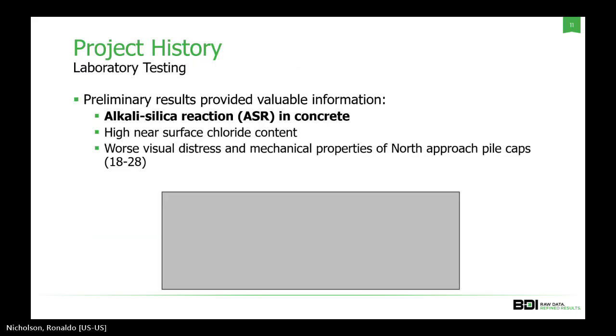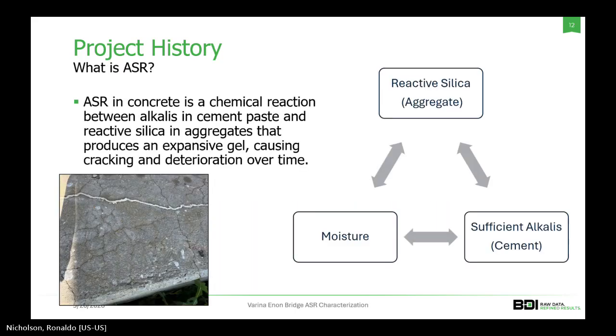Next slide, please. From these results, some of the valuable information obtained was that, in fact, they did have alkali-silica reaction in the concrete. They also had some high near-surface chloride contents, and in general, worse visual distress and mechanical properties of the north approach pile caps, which is why Parsons, in this case, recommended to start over there and perform sort of repair encapsulation. Next slide, please.